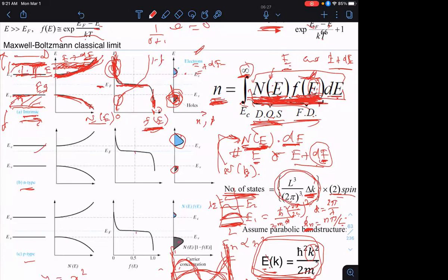So you have the number of electrons equal to the number of holes, and both will be equal to what's called the intrinsic carrier concentration, N sub I, which makes perfect sense because in an intrinsic semiconductor, I don't have any dopants. The only way I get electrons and holes is by directly exciting an electron from the valence to the conduction band, and that would create 1 electron and 1 hole, right? Equivalently, you can say that's breaking one of those covalent bonds, creating one conduction electron, and leaving behind the missing state, which is a hole.